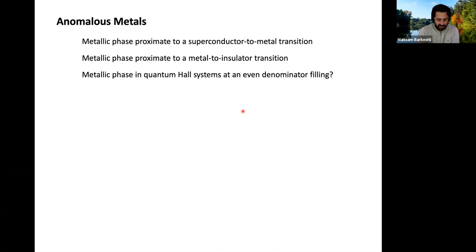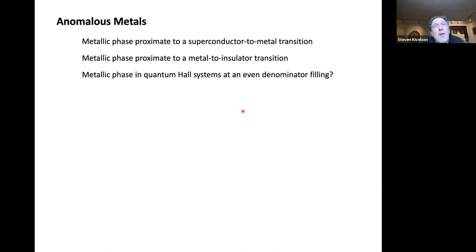What about, so you didn't really define incoherent metal. Incoherent metal and bad metal are basically the same aside from the resistivity? No, so a bad metal might well be an incoherent metal, but it's got something else. My assertion is that if I have a metal in which the quasi-particles have lost their coherence, then I would expect the resistivity to be roughly temperature independent and roughly the quantum of resistance, because there's nothing special going on here.